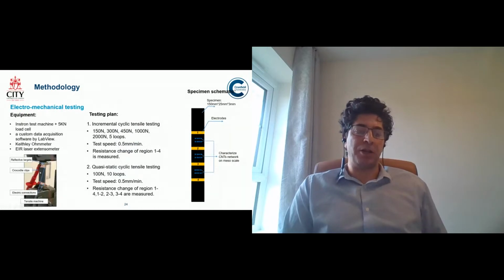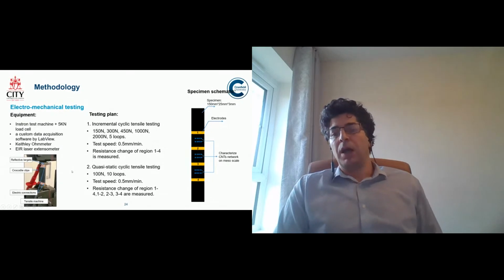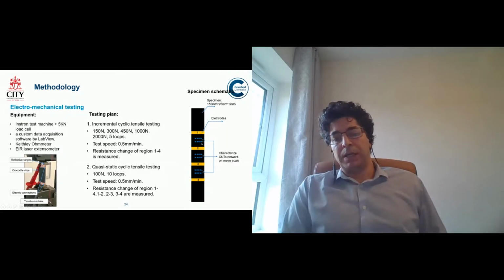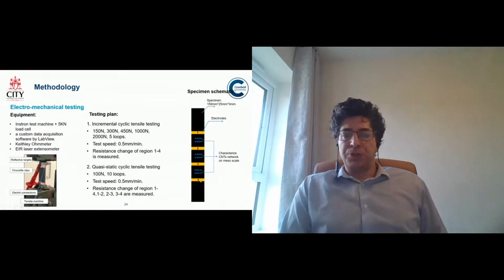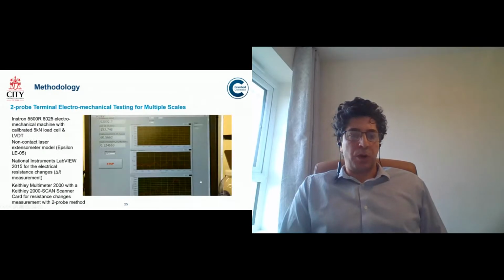We did, of course, the two-probe conductivity measurements, and we did the real-time strain measurement of these, cyclic loading and quasi-static loading only, at different, let's say, critical points of the specimen. That's just to give you an idea. The gauge length of the specimen from region 1 to 4 is about 14 millimeter. And as you just saw, some other information about what instrumentation was available, as well as our LabVIEW program to carry out this real-time measurement.